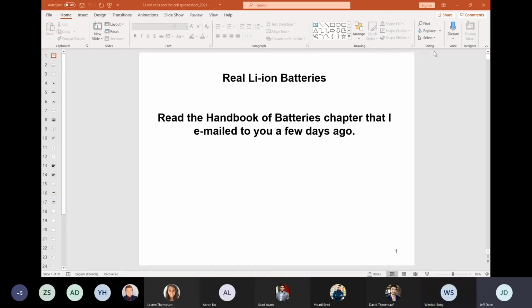But as an example, if you take lithium nickel oxide and fill it all the way to the normal point and then add more, you can go to Li2NiO2, and that plateau is at 1.8 volts, not so different than LTO. I see. So for this LTO structure, there has already been lithium inside. That's why the intercalation voltage is relatively low. You're adding more lithium to a structure that has already been lithium filled to some extent. It's part of the reason.